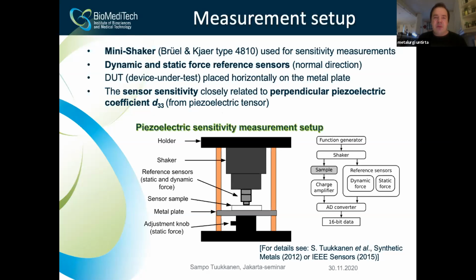In this kind of setup, we measure basically the normal force applied on this sensor element, and we measure the output. So this is closely related to the coefficient D33. This is the piezoelectric coefficient we are basically studying. I have to mention there are also other coefficients which are messing up the picture a little bit, because we cannot say for 100% that we are only measuring D33. There are always some shear forces and others which affect this. But theoretically, that's the case.